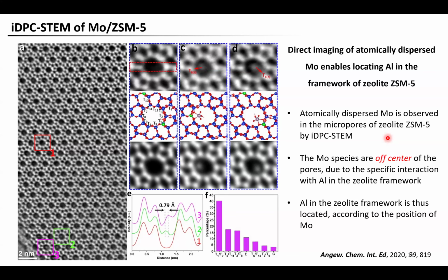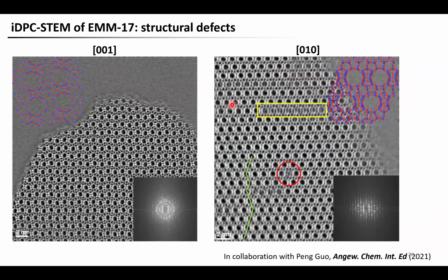For example, we investigated the distribution of metal clusters in zeolite ZSM-5. Similarly, a group at Tsinghua University in China used iDPC-STEM to visualize the adsorption of hydrocarbon molecules in zeolites. And we have also used iDPC-STEM to identify a lot of structural defects in another zeolite called EMM-17, including stacking faults, as you can see here, and some diverse structural defects that cannot be easily determined from the 2D image, but we can see there are many structural defects of different types.